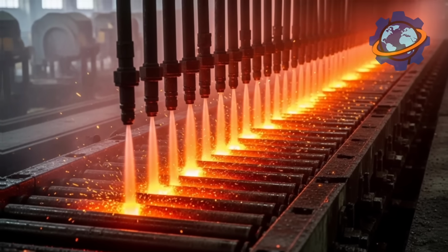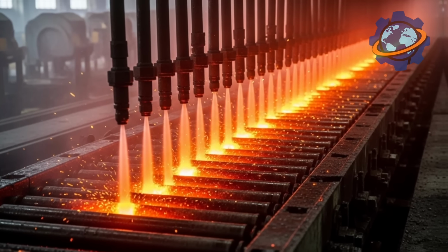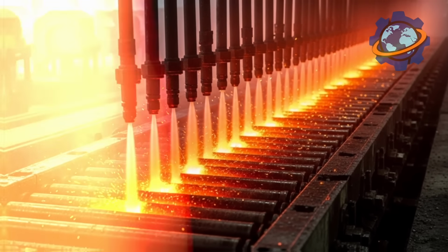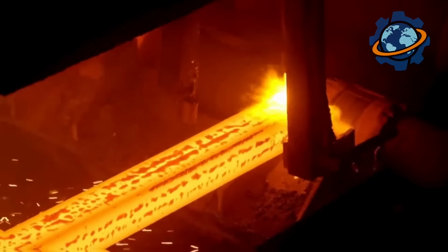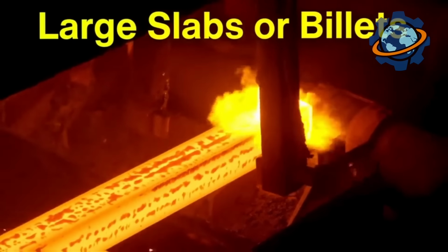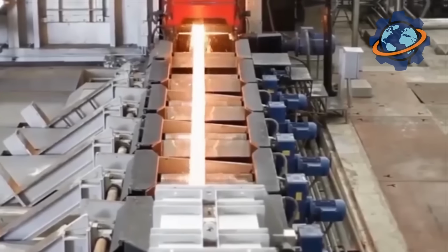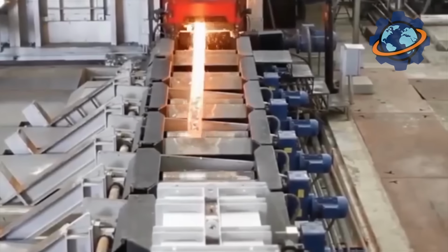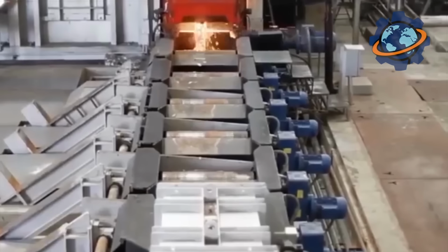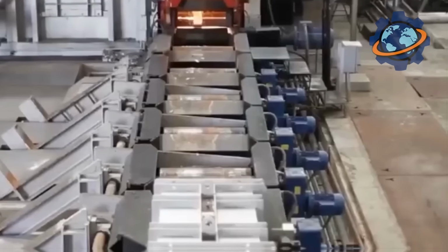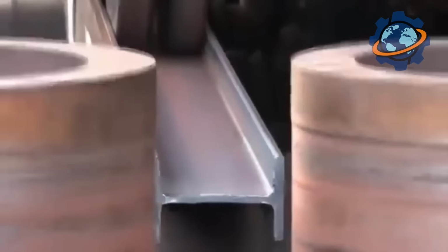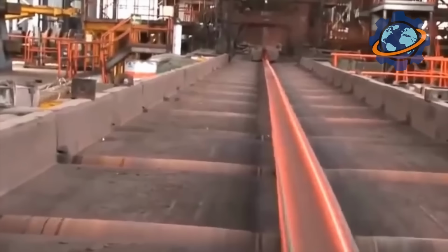After rolling, the rebar, still 800 degrees, enters a cooling bed where water jets control the cooling rate. Fast cooling creates hard but brittle steel. Slow cooling produces soft but weak steel. Controlled cooling achieves the optimal balance. Computer systems adjust water flow based on bar diameter, steel grade, and ambient temperature. The bars cool from orange to black in minutes, steam rising in clouds.